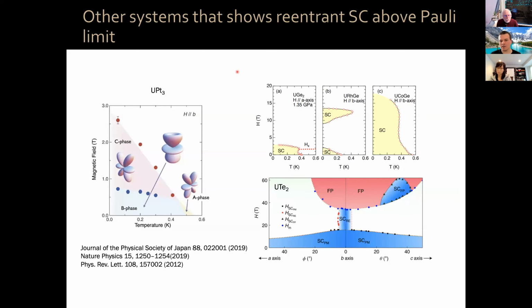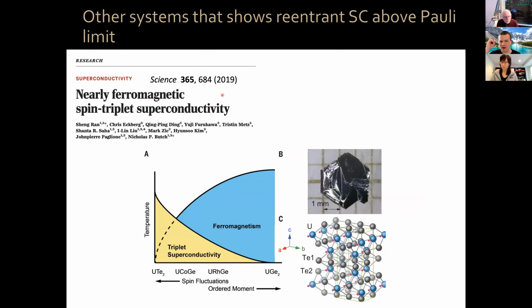In particular, the systems that show both of these behaviors are the uranium family compounds, okay? The most prominent are uranium germanium 2, uranium rhodium germanium, uranium cobalt germanium, and then ending with uranium Te2, okay? In these systems, you can have high field, reentrant superconducting phases, and this superconductivity violates the Pauli limit. Perhaps the most spectacular system is this recently discovered uranium Te2. All of these systems are either ferromagnetic or, in the case of uranium Te2, nearly ferromagnetic. Okay, and it is believed that these systems realize triplet superconductivity, in particular in the case of uranium Te2.